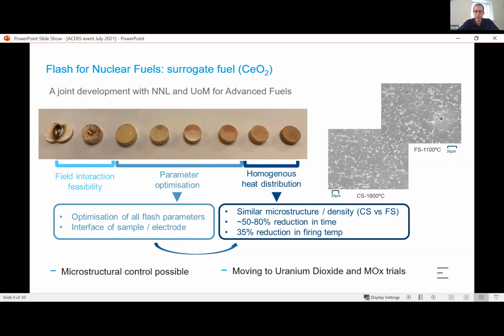And again, that was done at a 35% reduction in firing temperature and a 50 to 80% reduction in time of sintering. So some real benefits of application. We also showed that microstructural control was possible.